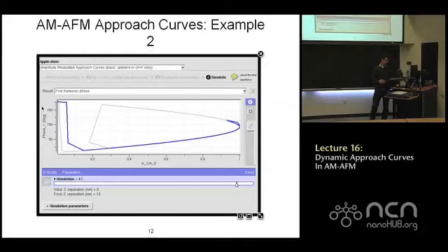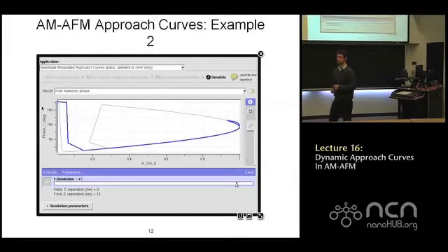Technically you can measure mean force in amplitude modulation AFM, but you're much better off looking at the phase of the oscillation. Mean force is probably pretty small, and it's not always easy to measure mean deflections with high resolution. So what you would look at is the phase of the oscillation.